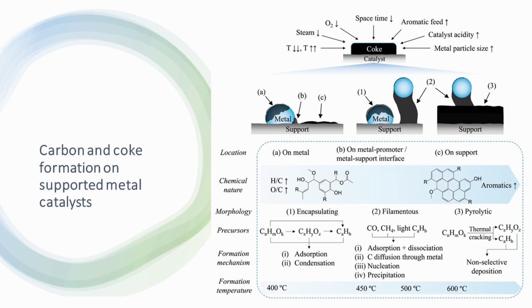In coke-sensitive reactions, unreactive coke is deposited on active sites leading to activity decline, while in coke-insensitive reactions, relatively reactive coke precursors formed on active sites are readily removed by hydrogen or other gasifying agents.